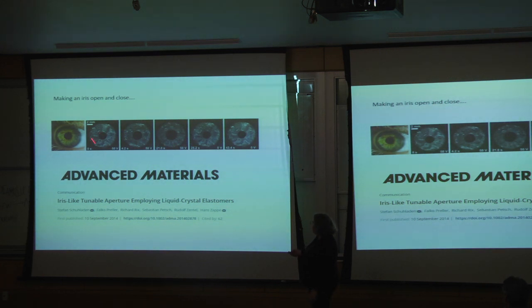So here he has a hollow disc, a disc with a hole in the middle. I guess I would call it an annulus. And the nematic director is parallel to the radial direction. And embedded in the nematic director is a little bit of wire. It's like a heating element, and it's curled up. Maybe it just wiggles back and forth along the radial direction. And when he heats it, he can make this hole open and close. So we decided we would model that too.